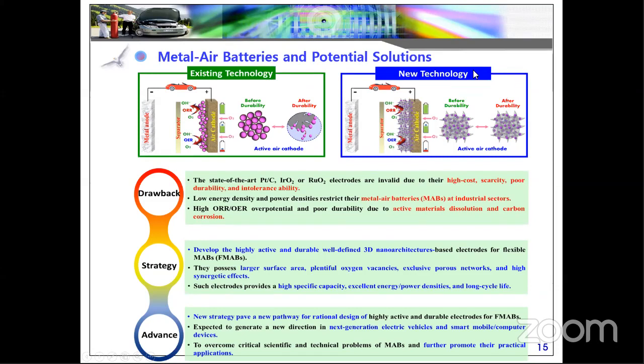What new technology are we going to develop compared to the existing technology and its problems? With platinum or ruthenium oxide based catalysts, when we mix them, ORR happens on platinum carbon and OER happens on ruthenium, in a 1:1 ratio of ruthenium and platinum carbon. Then we coat the material and use it as the air cathode for metal-air batteries. During long-term durability tests, due to carbon corrosion, the metals dissolve into the electrolytes, and the stability is very questionable. That's why, to avoid this issue, we need to develop 3D nanostructure materials.